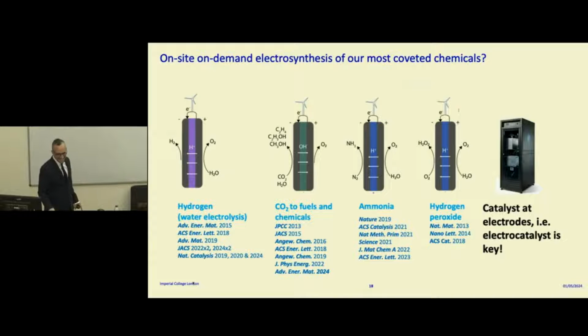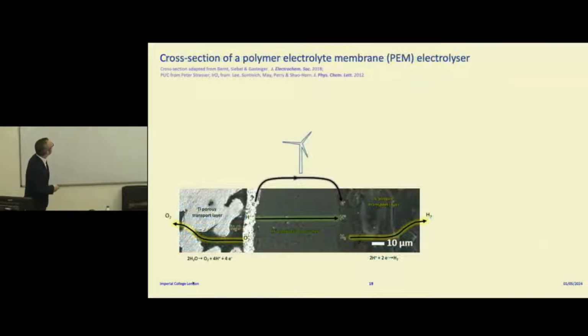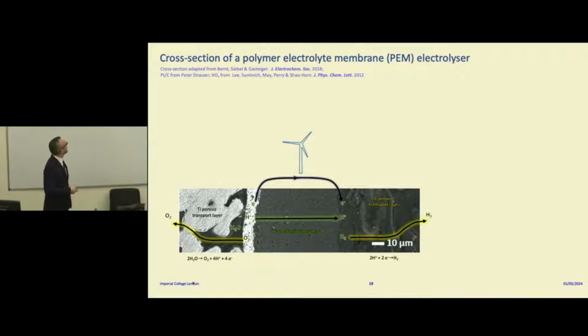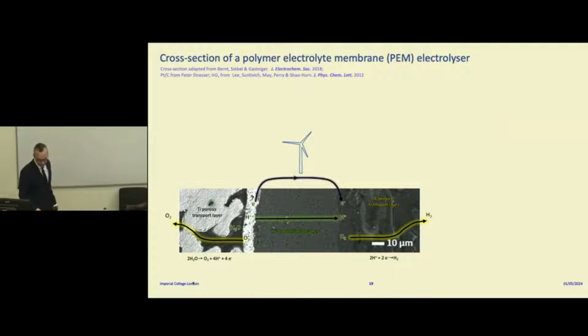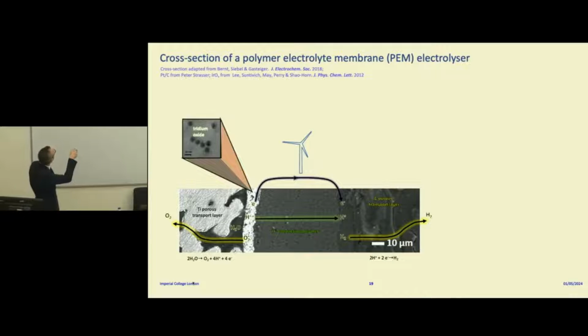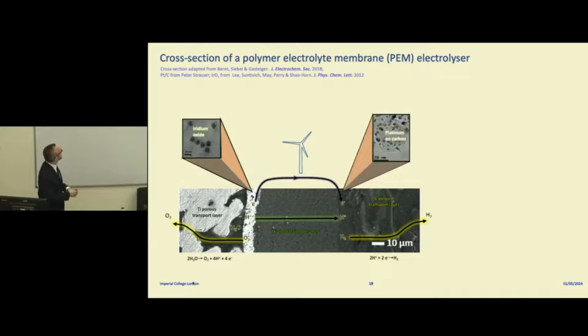To appreciate what a catalyst is, I've got a cross-section here of a water electrolyzer. An electrolyzer is a means of making hydrogen. Essentially, you split water into hydrogen and oxygen using electricity, ideally from renewables. You have in the middle a membrane that only conducts protons, and at the sides you have the electrochemical reactions. You have hydrogen being evolved on one side and oxygen being evolved at the other side. The electrocatalysts are actually these little nanoparticles here. You have iridium oxide nanoparticles at the anode electrode, and you have platinum dispersed on carbon at the cathode.